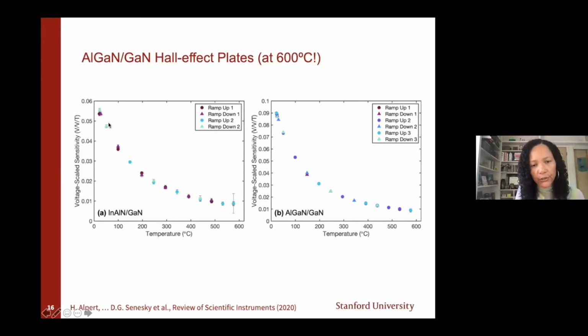And then she's continued to ramp up and down. And we can see that these curves overlap with each other. And so there's repeatability, and we can see that we are actually, due to these thermal cycling, not showing any major degradation in our devices. And that tells us that our ohmic contacts are very stable, because this is a device that uses ohmic contacts. We haven't really introduced the Schottky contacts yet. I'll talk about that in a moment, but we're really happy with this result.